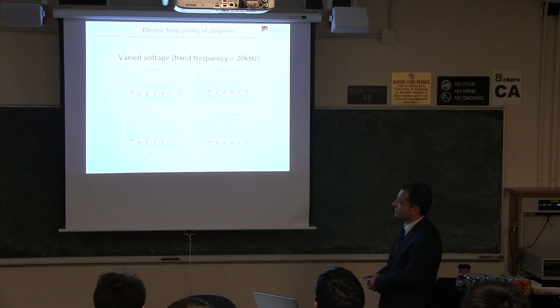That's where we live in organics, but it's sufficient for most of our devices. Actually, these numbers are a little bit low. We can get up to 10 to the minus 2 or 10 to the 0 in some cases. So basically, with all these geometries we tried of different channel lengths and widths, for the most part, the mobility goes up by a factor of 2 to 5 when we apply electric field.